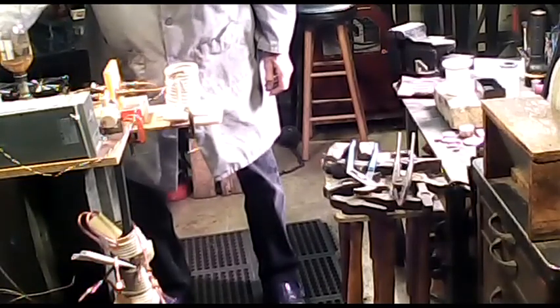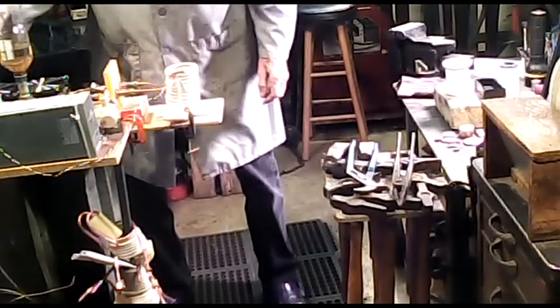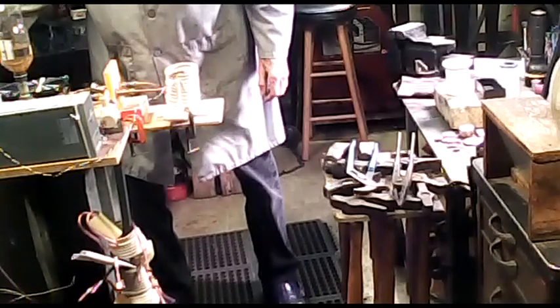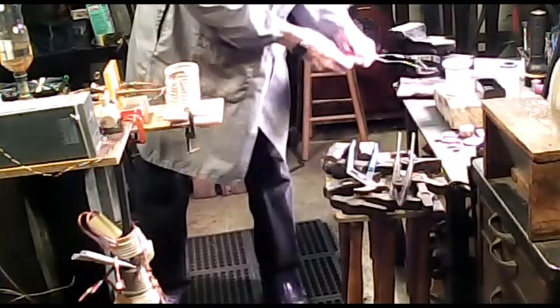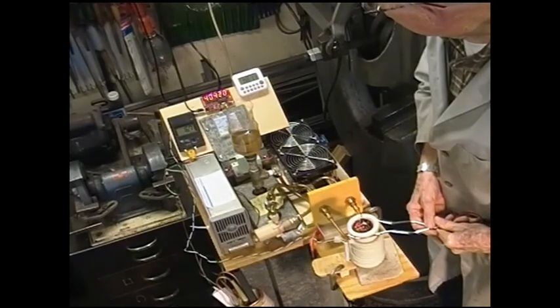Just turned the current on, 6 amps idle, 16.1 Celsius on the water cooler, 37.8 frequency, and we will start the timer and put the material into the crucible. Current 10, 20, 25, 30, 32, 34, 37 amps, 42.4 kilohertz, 23 seconds in, 16.9 degrees Celsius on the water.